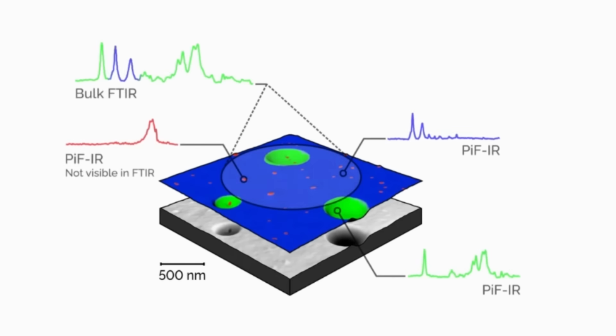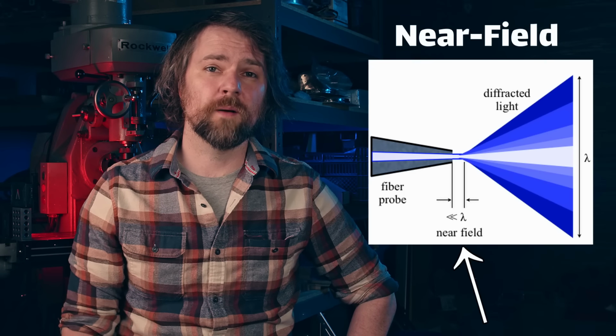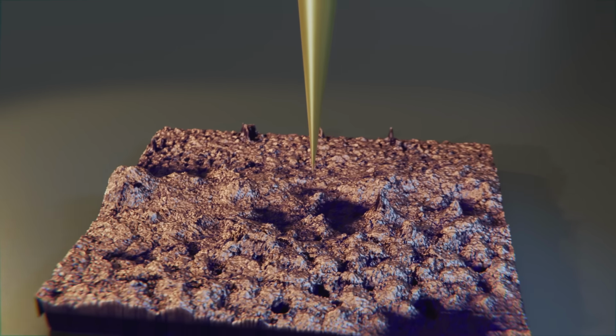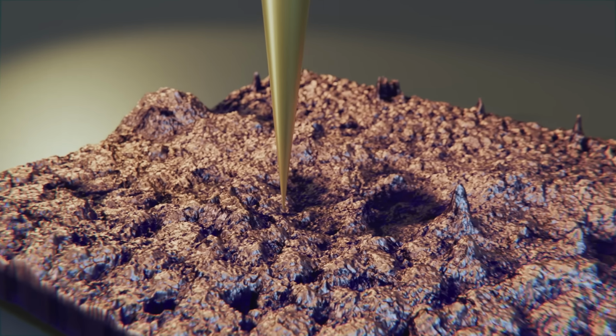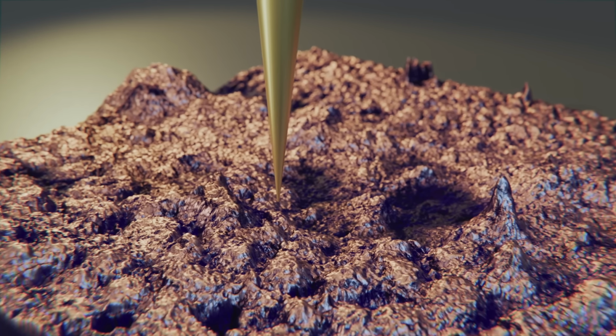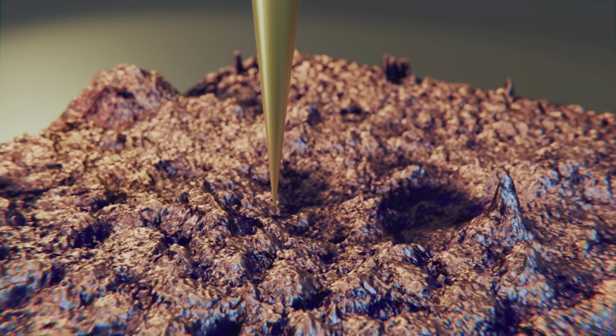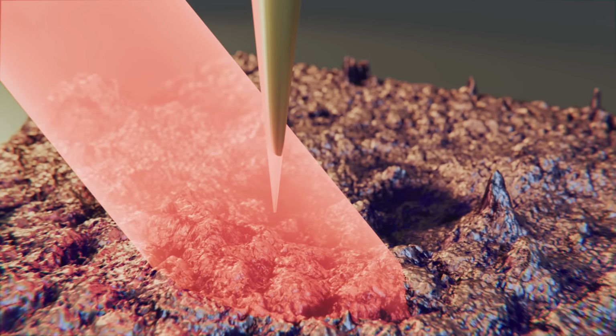That's what makes the Vista microscope so interesting. It can collect IR spectra down to about 5 nanometers spatial resolution, which is clearly way below the diffraction limit. It does this by exploiting an optical phenomenon called the near field. A metal-coated probe is positioned near the surface of the sample. We're talking like within 10 nanometers of the surface. A laser is then focused on the tip and the sample.